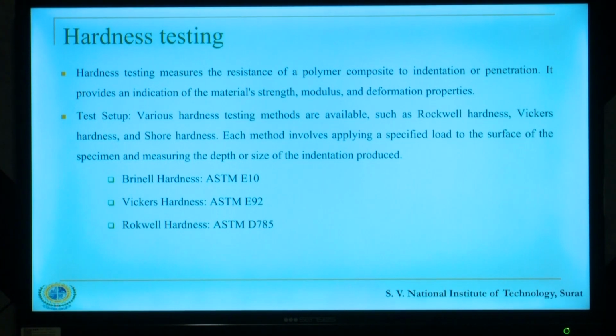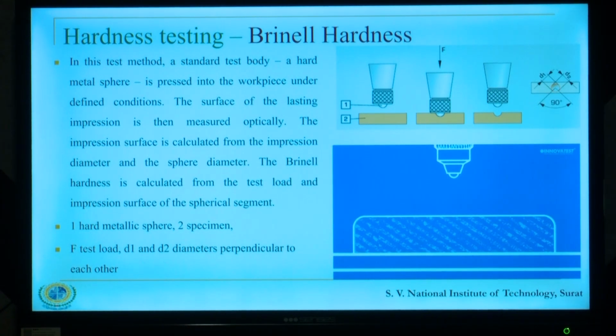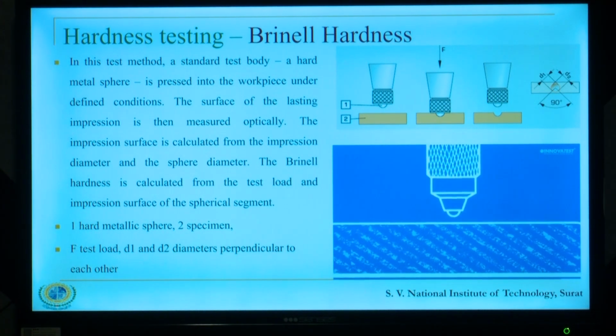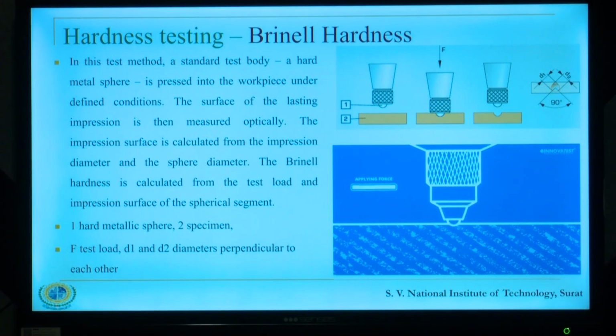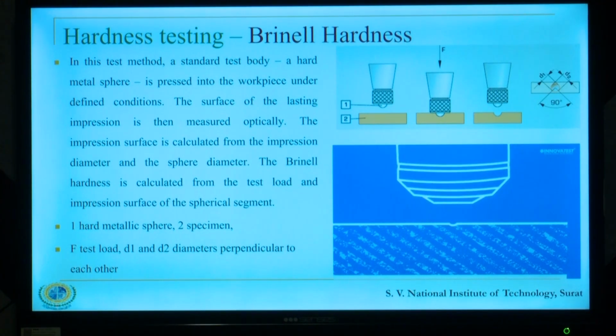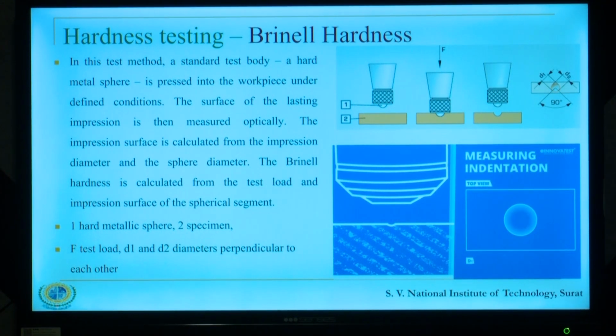Hardness, usually we go for 3 different sets of hardness testing depending on different conditions. Often this goes with the facility that we have. So in case of Brinell hardness, our indenter is a sphere. You measure 2 values of diameter of indentation, and it gives you the value.